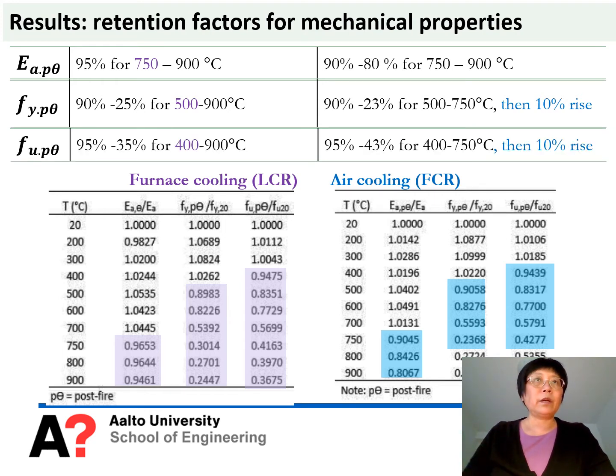And for the furnace cooling, the retention factor is about 95% to 35% when the cooling temperature is between 400 and 900 degrees. But for the air cooling, the retention factor for the strength is about the same, but only when the cooling starts above 750 is there some rise of about 10% in the retention factor.